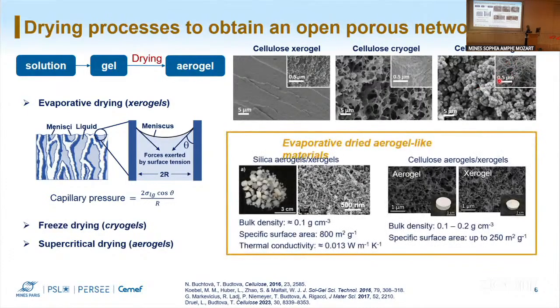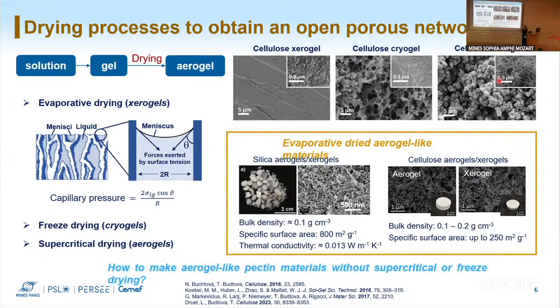There is work done to bypass supercritical drying and obtain materials with good properties by evaporative drying, and only for silica and cellulose these have been achieved so far in the literature. So the next question is how to make aerogel-like pectin materials without the use of supercritical or freeze drying, sorry, so with evaporative drying.